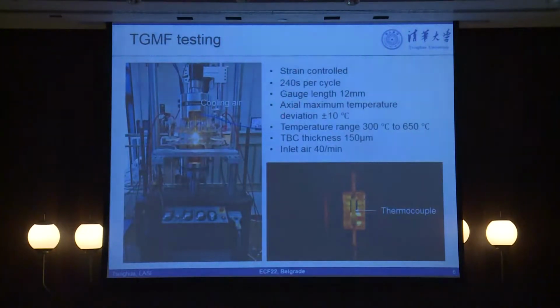In our case, we test different materials. In the present talk, I'm going to talk about just conventional nickel-based alloy, and the working temperature for that superalloy is limited up to 650 degrees C. We also test other materials, for instance the CMC, the ceramic matrix composite, or single crystal superalloy. In that case, the temperature is higher. What you see here is a picture we made. As you see, the specimen goes around the radiation. The oven temperature is not high, but you focus here, and the specimen temperature becomes very high. You can change the temperature very rapidly.